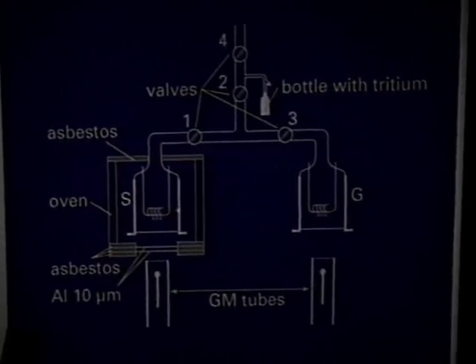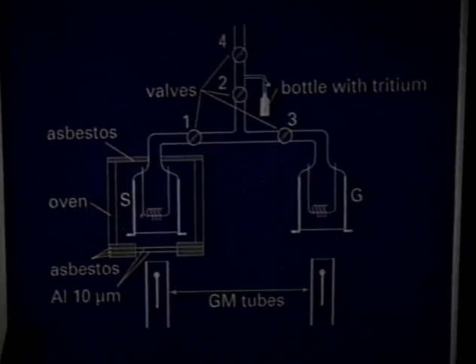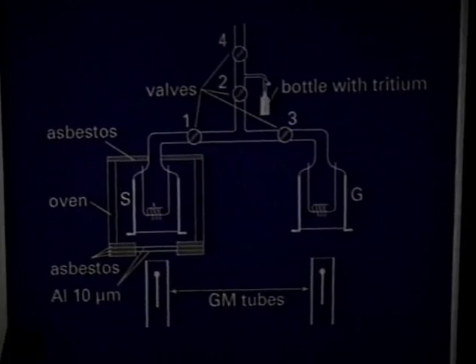In tube S, we made a preparation of 48 milligrams in both tubes. We made the preparation of the finely divided titanium of 48 milligrams. And in tube S, we absorbed 1 curie of tritium in the titanium preparation. This tube was placed in an oven, and during heating, the tritium released from the preparation in tube S was absorbed by the titanium preparation in tube G. Therefore, with this GM tube, we measure the gas which is released during heating from this preparation.